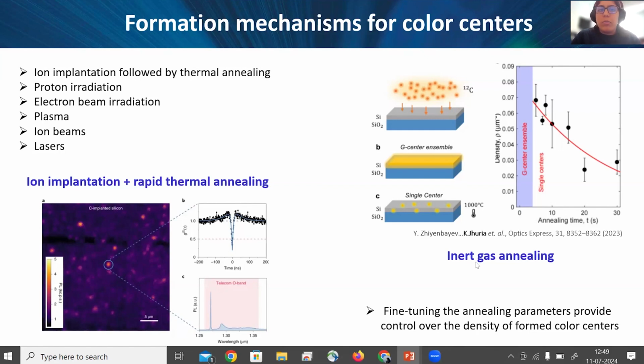And then if you play around with different recipes, for example, if you change the annealing parameters, like the annealing time and the temperature, you can tune some properties. For example, you can tune the density. There's a nice window for your annealing time where you get single centers in the silicon. If you are outside that window, then you have more chances to have clusters of these defects. So you can do some fine tuning with these parameters.